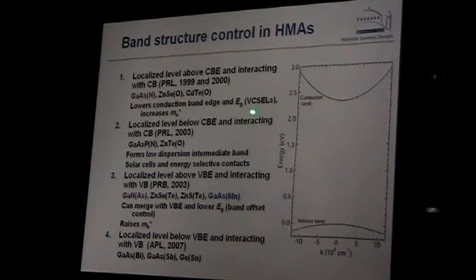Let's take a semiconductor with valence band and conduction band, and we can do many different things with this. For example, we can sometimes put the element's impurity level into the conduction band. This is the case of nitrogen in gallium arsenide, or oxygen in zinc selenide. You can also use some other semiconductor, and this level of nitrogen or oxygen will now be below the conduction threshold. This is the case of zinc oxide telluride or gallium arsenide phosphide nitride. So we can move this around.